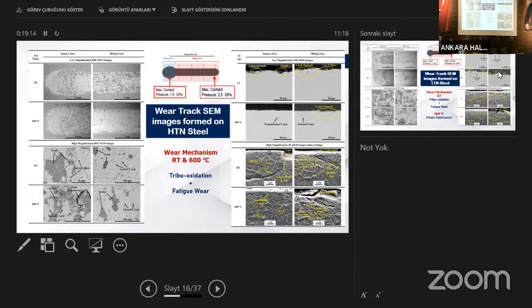This is the result of the high temperature nitriding material. This is the worn surface. Please notice those cracks, right? Those are the indications of fatigue wear. So the surface has been exposed to fatigue. When we look at the cross-section here, the cracks that initiate on the surface propagate right here. There's spallation and crack propagation towards this line. The test was conducted at room temperature as well as 600 degrees Celsius, but at both temperatures, the main mechanism was fatigue. Additionally, those dark colored regions are oxide, so some evidence of tribo-oxidation has also been detected, but the main mechanism is fatigue.